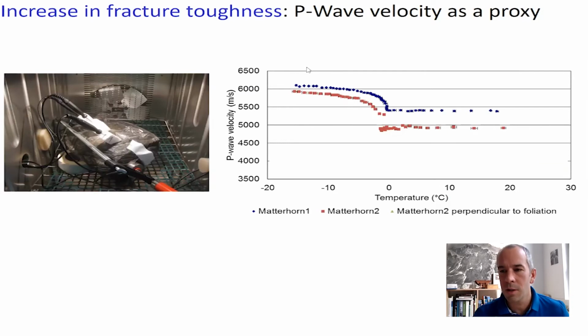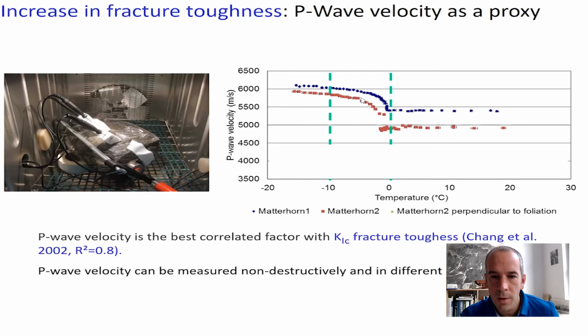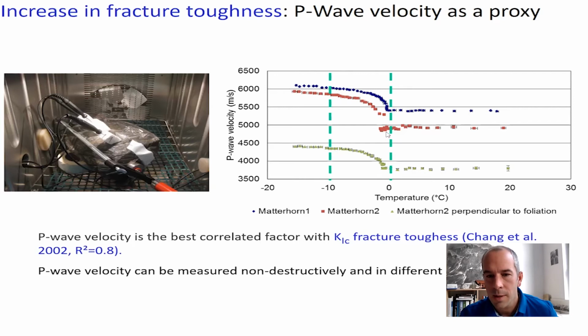The same is true for P-wave velocity. Here we send a P-wave through the rock sample from the Matterhorn, and we look at what happens at the freezing point. You see, the freezing point is -0.9 degrees here. And upon freezing, you see that the P-wave velocity rapidly increases. This is also mechanically quite interesting because the P-wave velocity is the best correlated factor of the fracture toughness. So we know between -5 and 0 degrees, we have a massive change in the fracture toughness in these rocks.